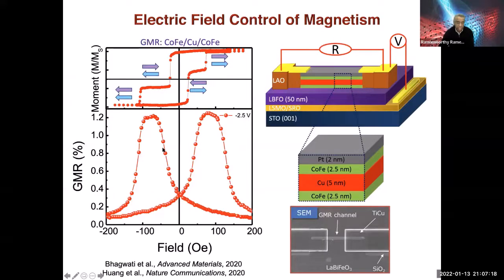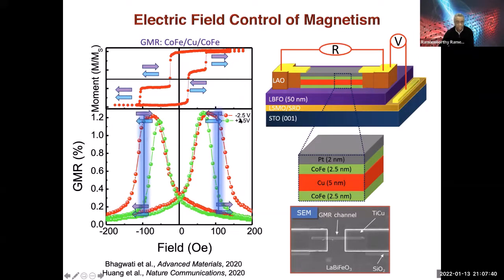And this is the details of that. You can see that in the GMR structure, the bottom layer is magnetically coupled to the LBFO, and therefore has a higher coercive field of about 120 oersteds, and the free layer, which is the top layer, has a lower coercive field, typically around 20 oersteds. And then when you apply an electric field of minus 2.5, you see this GMR behavior. With plus 2.5, you can manipulate that. And so we showed that, indeed, you can manipulate the magnetic state of the bottom layer. And this GMR was basically a readout mechanism. It's not what you would use for a real device.